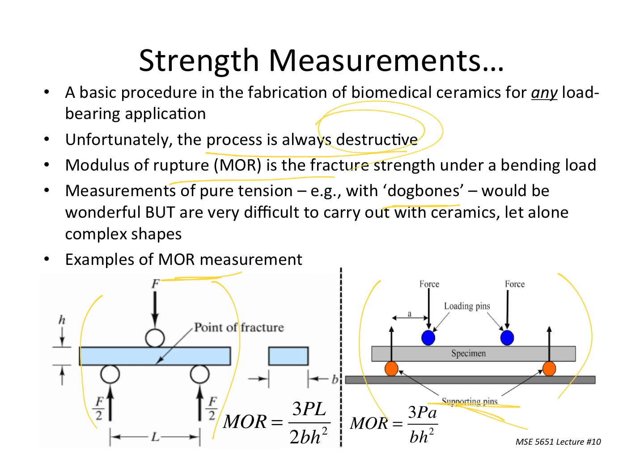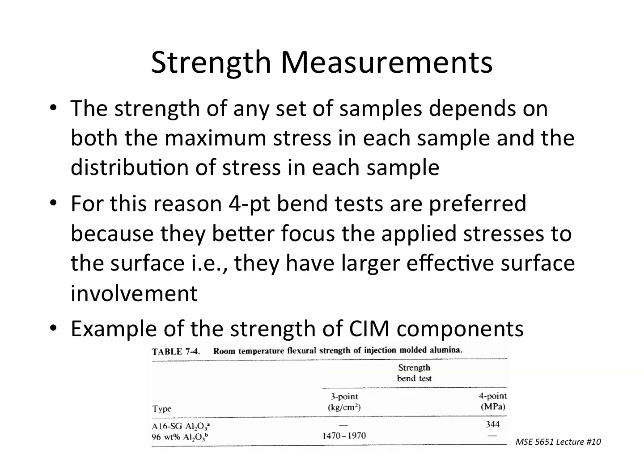And it's always destructive, meaning that we lose that part, but hopefully it came out of the furnace with 100 other sister parts, and what this one part that is destroyed will do is tell us something about all the sister parts that came through the same furnace. Surface, as you see here, this surface is we're trying to stress that surface. Now, it's a ceramic, it doesn't visibly bend, but we know we maximize the surface stresses. All right, and so the strength of any set of samples depends on both the maximum stress and the distribution of stress. 4-point bend tests, because they tend to focus the stress, not just through the whole microstructure, but on the surface of the opposing side. And so we get a better idea of what's being stressed, where the flaws are coming from, and so forth.